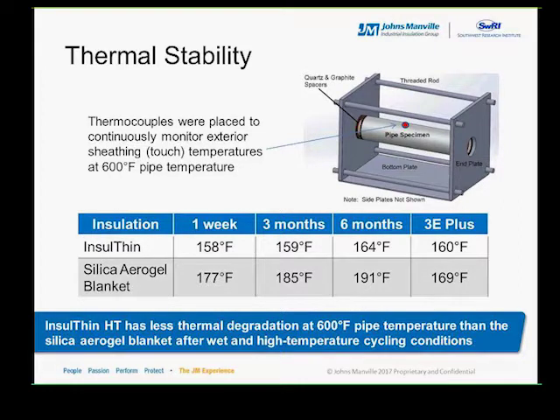So switching now to the impact of real-world accelerated corrosion conditions on insulation thermal performance, what we did is we evaluated the thermal performance of both insulations at different times. You can see in this table that we looked at it from a perspective of 1 week, 3 months, and 6 months. How we did this is we placed a thermocouple at the outside of the sheathing in the high temperature cyclic assembly and measured the temperatures when the pipe was at its 600-degree time cycle.